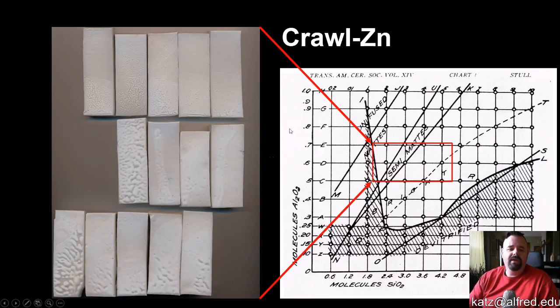Okay. Now we do get several effects, and this is what Rob figured out that was so smart, which is as you increase the alumina, you get different glaze fit, and we'll look at how the glaze fit works in a second, but you get different levels of crawling. Very fat, and it gets thinner till it gets very, very thin with higher alumina levels. This line is 0.7, 0.6, 0.5. Again, working within the matte glaze phase field across that glaze formation boundary.